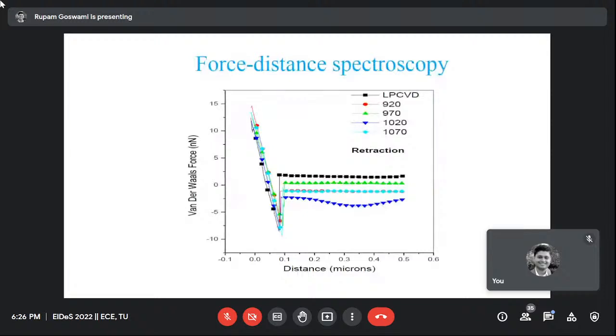Because in polysilicon, if we compare with crystalline silicon, for the piezoresistive coefficients the grain size and the grain surface energy are extra parameters which are not there in crystalline silicon. So this way, perhaps we can have a tuned, varying performance of the device by choosing these routes, and we can bring these things to have the desired performance of the pressure sensor. Next, please.